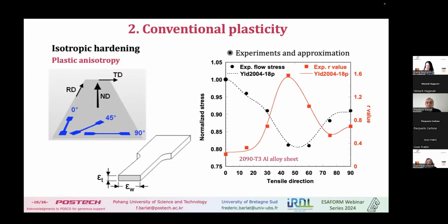So the black dash line represents the anisotropy curve of the flow stress with a scale on the left side in black also. And all those points are the experimental points measured every 15 degrees. Now the red curve represents the R value, this strain ratio, and the square symbol. And you see that with this yield condition, we are able to represent the plastic behavior quite well. Of course, this is a fit here, okay? I don't pretend this is a prediction. This is a fit, but the thing is that with Hill 48, for instance, it's impossible to do such a good fit. And so that's why it's important to get the right model.